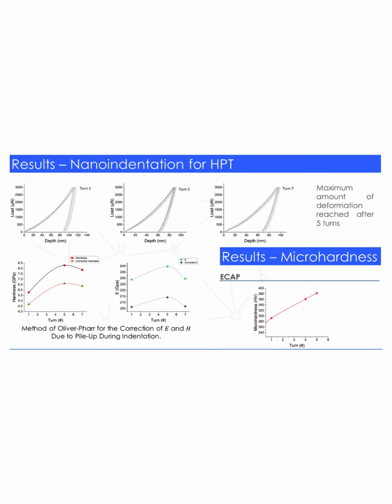This is because the actual deformation applied to the sample and its influence reach their peak after 5 turns. Further processing results in the cancellation of deformation cells and microstructural defects, in addition to the creation and growth of cracks, which also decrease the mechanical properties of the steel. In the case of ECAP, micro-hardness tests show that as the number of passes and therefore the deformation increases, the hardness also increases. However, due to the limitations of the ECAP press, tests could not be conducted beyond 5 turns.